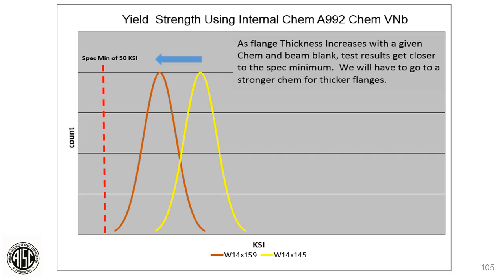Now, here's what happens. You have process variation. For example, for W14x145, the LMF operators aimed for a specific manganese, and a specific vanadium and columbium in this case. This is an internal chemistry of this producer, called Chem VNB. Now, if they take this exact same chemistry, even from the same heat, and roll it to W14x159, they could find that they're getting close to the minimum yield strength. Minus 3 standard deviations would be too close to the spec minimum. That's fine, we're still meeting specifications, but if we're going to W14x176, a new chemistry is going to have to be used. So the next slide.